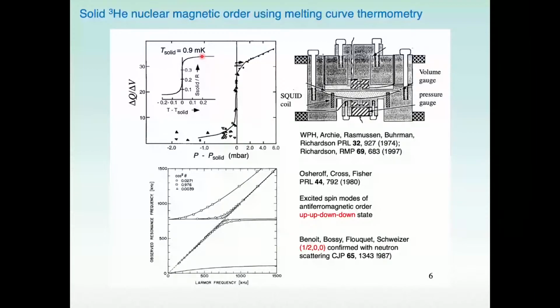What I'm showing on the right-hand side in the main figure is actually the measurements of heat inserted and the corresponding volume change to measure for a measurement at a constant pressure. And those measurements indicate directly this decrease in the entropy. That entropy was then reflected in the properties of single crystals of solid helium-3, which I'm going to tell you about in just a minute.